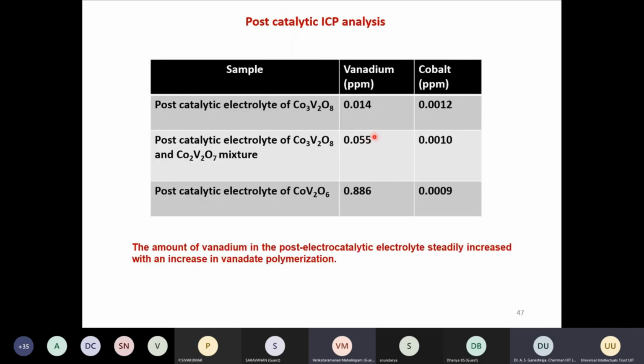Okay, so this is again confirmed from the ICP analysis of the post-catalytic electrolyte of Co3V2O8, where you can see the vanadium and the cobalt ratio. Here you can see the post-catalytic electrolyte for this sample and this sample. You see a very high concentration in one, whereas it's a very low concentration in the other. That means here there is vanadium leaching, and here there is no leaching. Whereas the cobalt is more or less similar. It's not really much leached out. So cobalt generally doesn't leach out, nickel doesn't leach out much, but the anions leach out, which improves the activity, which is what we wanted to tell with this one.